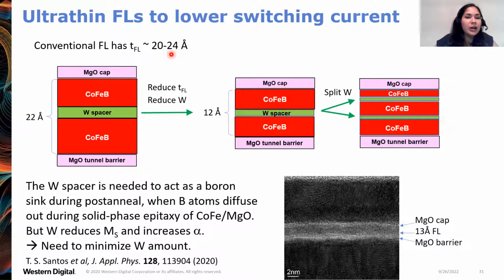So the free layer conventionally is about 20 to 24 angstroms thick. It's made up of cobalt iron boron alloy on top of the MgO tunnel barrier with an MgO cap at the top. And somewhere inserted in the middle is typically a heavy metal spacer. In this study, it's tungsten. And the purpose of the tungsten is to give the boron atoms a place to go when you're doing this post-anneal step. You want the boron atoms out of the way to allow this solid phase epitaxy of the cobalt iron and the MgO to get high TMR.